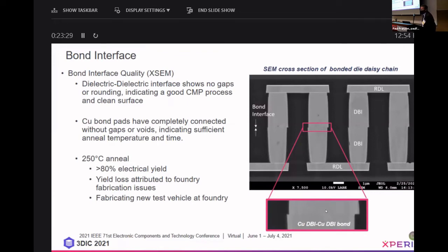With the 250C anneal, we're getting better than 80% electrical yield on these large chains. Some of the yield loss is attributed to a foundry fabrication issue we had, because we had actually requested a sort of non-standard process from the foundry with a single damascene DBI process, where they normally do a dual damascene process. And so we're fabricating a new test vehicle now, which we expect to give higher results in the electrical yield.